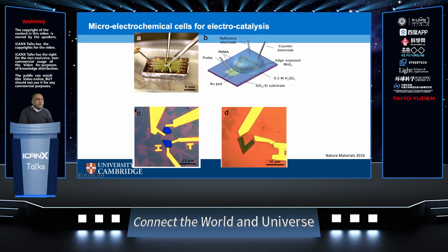And what we're interested in is to understand what the influence of the charge transfer resistance is. So in this kind of device, that would simply be the contact resistance between the molybdenum disulfide and the metal contact. We're also interested in whether the 2H phase is active for HER or the 1T phase is active for HER. And so we can open up very well-defined windows by lithography. So the electrolyte is only exposed to specific regions of the MoS2, two-dimensional MoS2 nanosheet.